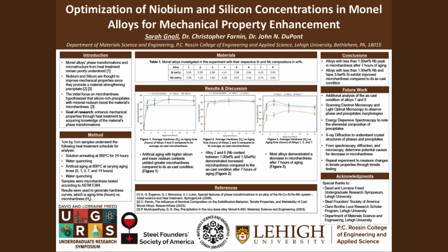Niobium and silicon, two elements that are found in Monel alloys, are thought to improve mechanical properties since they promote a material-strengthening precipitate. Therefore, the goal of this research is to enhance mechanical properties through heat treatment by acquiring knowledge of the material's phase transformations, allowing us to determine what ideal combinations of niobium and silicon would best serve for better mechanical properties. Myself and the collaborators on this project initially focused on microhardness, so it was hypothesized that silicon-rich precipitates with minimal niobium will boost the material's microhardness.